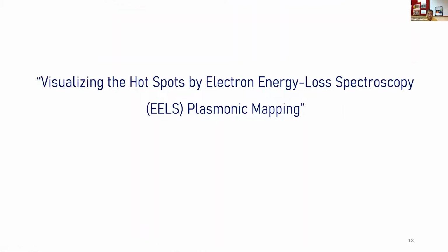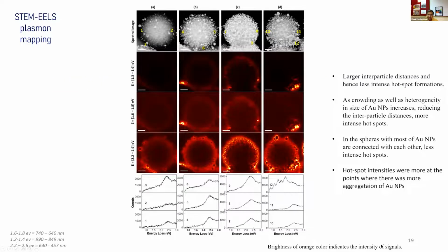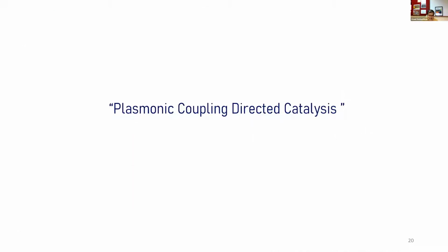We also wanted to visualize these hotspots. So we did EELS mapping, electron energy loss spectroscopy mapping, and the brightness of the orange color indicates the intensity of the signal. You can see when the particles are coming closer and closer, they are becoming brighter and brighter. But when the particles connect with each other, that brightness went down because you want a gap between them to have these hotspots. Otherwise, there will be no hotspot. So these STEM-EELS maps also indicate that by tuning the gaps, one can tune the intensity of the plasmonic, electromagnetic hotspot. Okay. Then we wanted to see whether we can use these materials for catalysis.